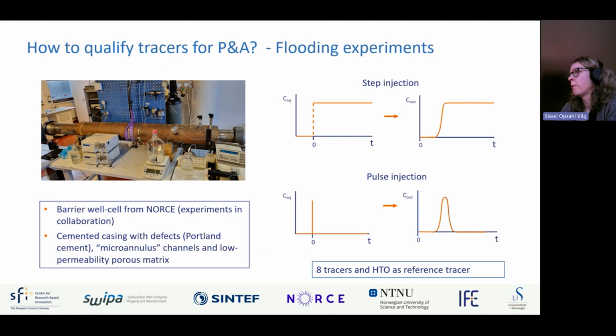We did two types of experiments in this one. One was a step injection, and to perform this experiment, we inject the tracer continuously into the fluid flow, and it's moving through the plug, and then it's produced, and we continue the experiment until we reach a stable level of the tracer concentration at the outlet, where the concentration at the outlet matched the concentration in the injected solution.